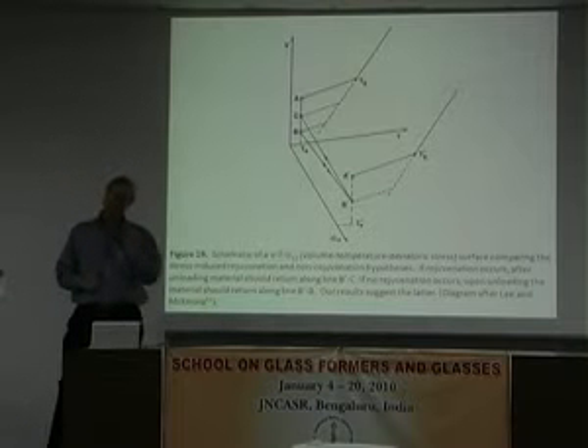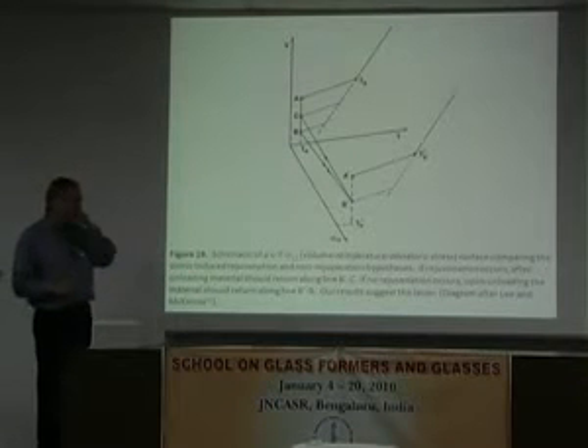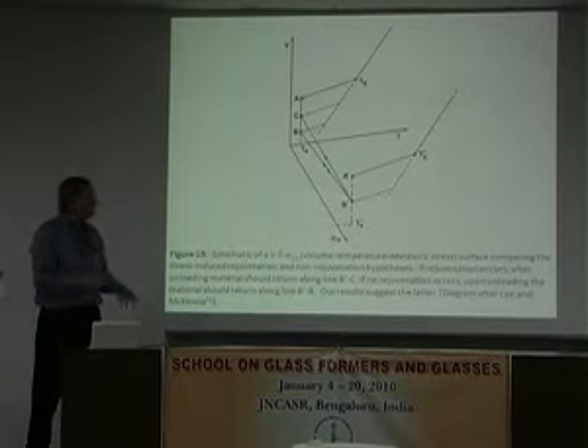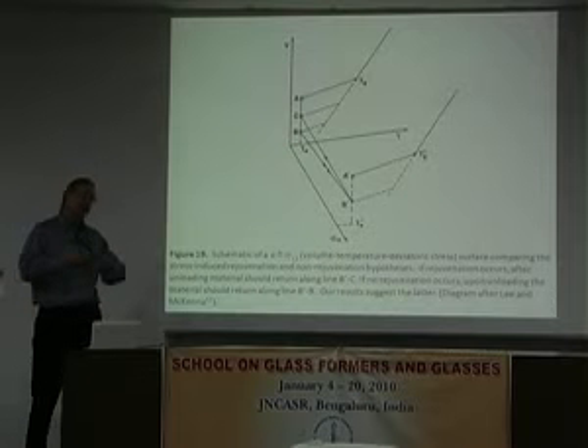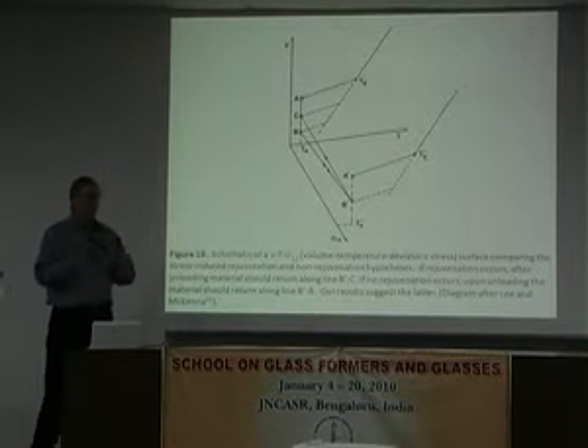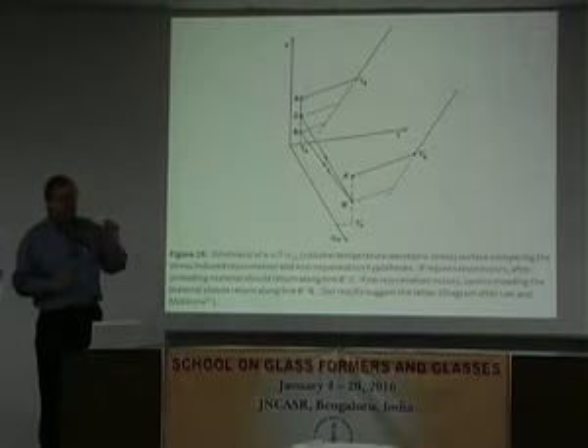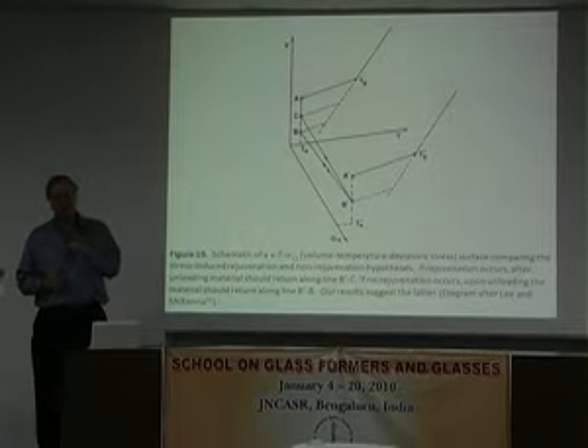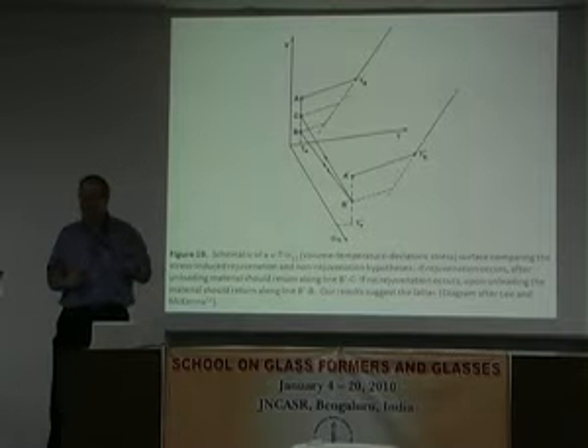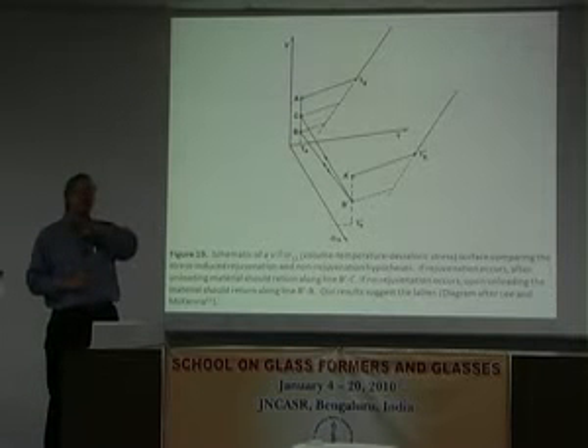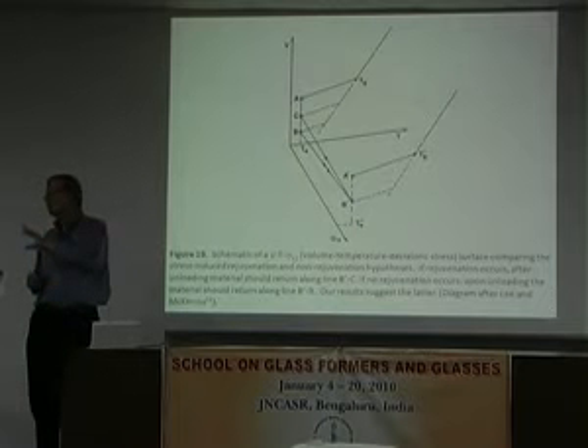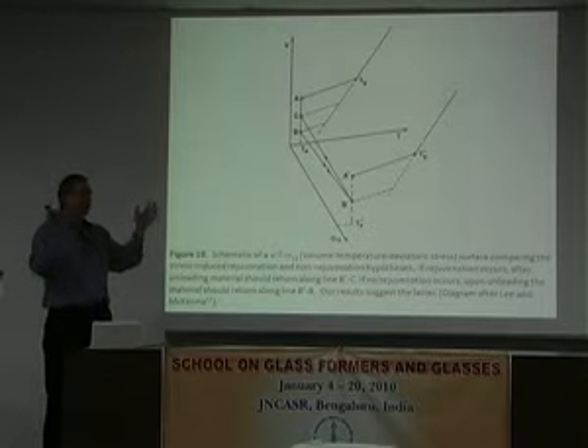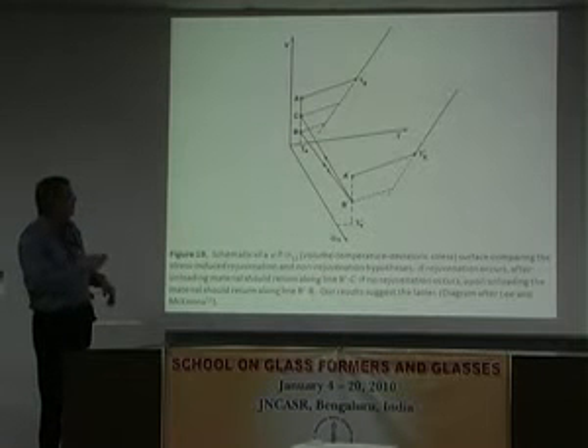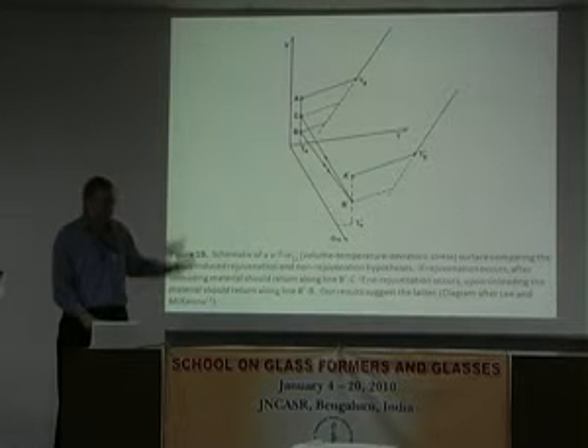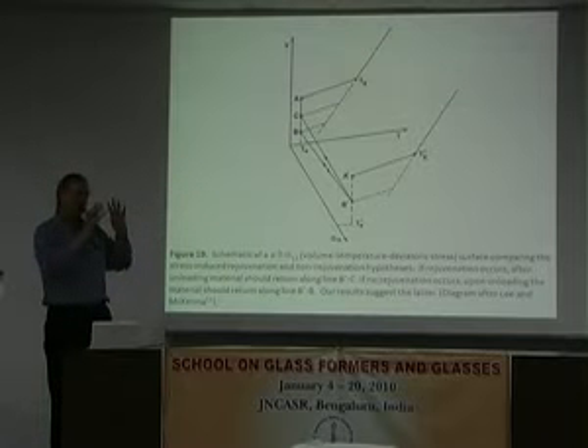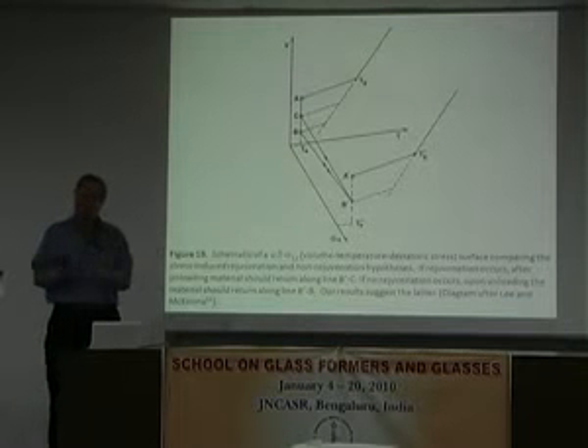Now, there's been some work with computer simulations and energy landscapes that Dan Lacks has done, and close to Tg, where we did our experiments, he's more or less in agreement with this picture. As you get to other conditions, you get different results. The thing that he does find, however, is that from his energy landscape picture, the mechanical rejuvenation changes the landscape differently than if I had done a temperature jump. So maybe in that sense it's much like the humidity jumps, in that I get to a different glassy structure. Anyway, this is how we were looking at it at the time, and I think these pictures have evolved a little bit, but this really means that erasure and rejuvenation, as originally postulated back in the 80s and 90s, is not quite the correct picture.